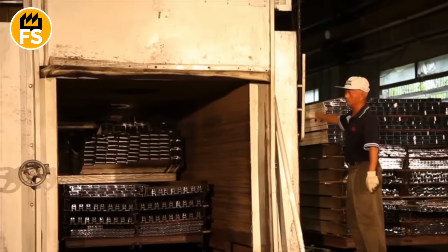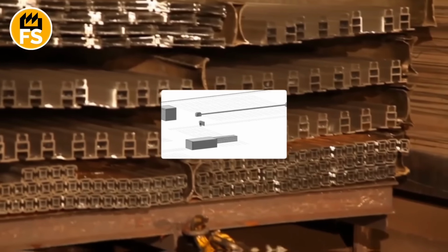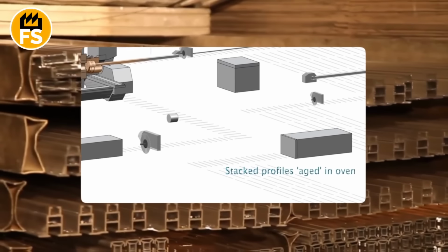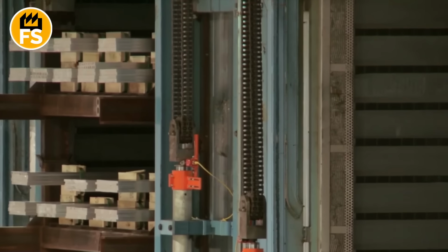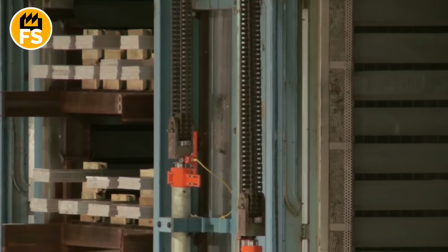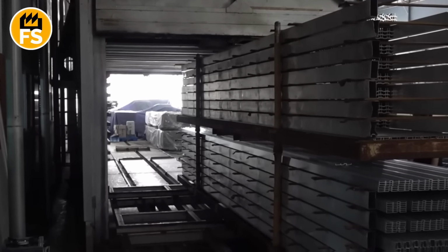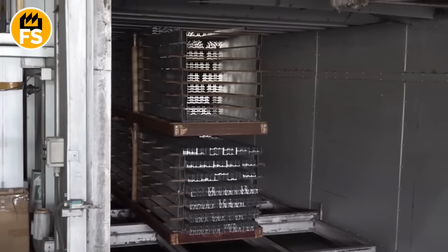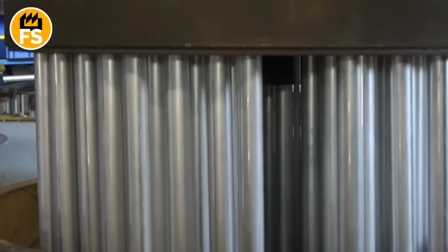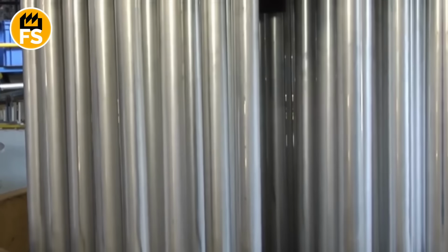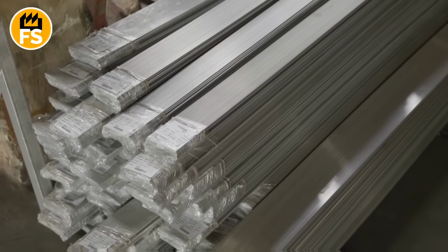The final touch? The aging oven. Cut profiles get stacked into baskets and sent into an oven where they bake for several hours at around 400 degrees. This completes the formation of the metal's internal armor once and for all. What comes out is the exact same part you see in your window frame or solar panel structure. Lightweight, perfectly straight, and incredibly strong.